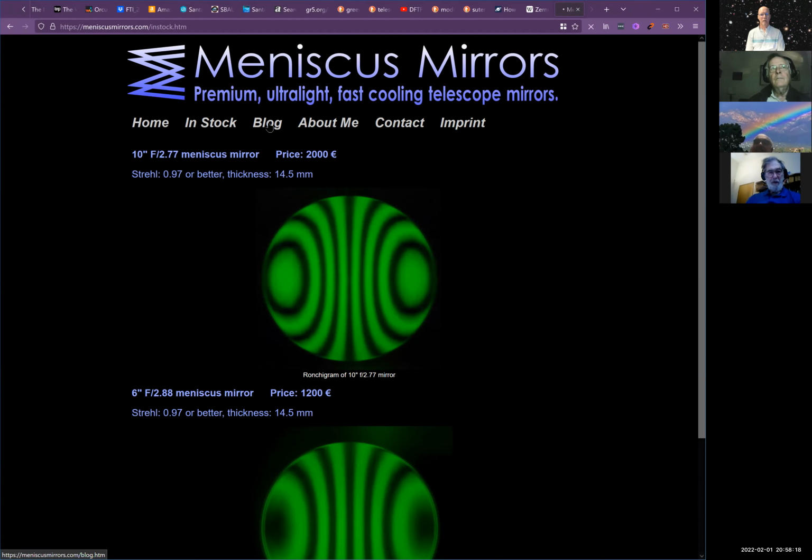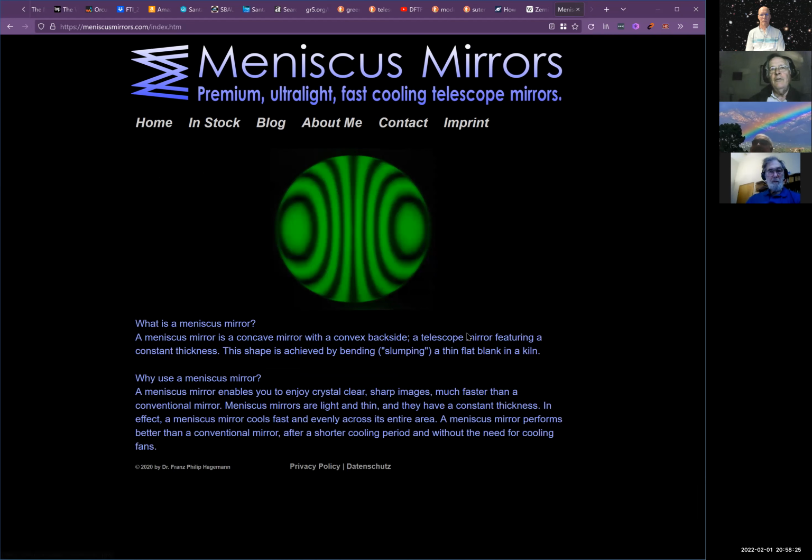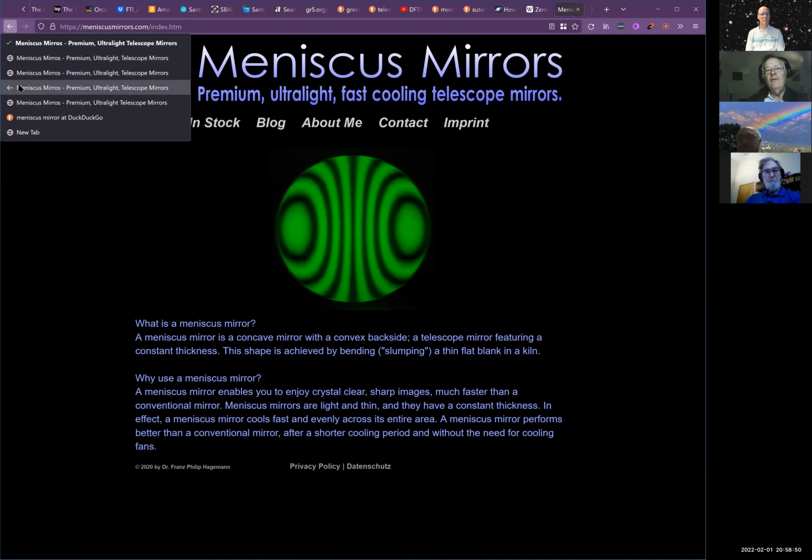Still first surface aluminized though, right? Yeah, but some of these other guys, they're not going with aluminization. They're going with silvering. That's being a big push. When you've got a 30-inch mirror and you're on retirement, it's not very affordable. There was a big article on that, about how people were going back to silver. Yeah, they're actually getting pretty good results, and they're talking about getting anywhere between 1 year and 5 years of use out of a silver mirror.